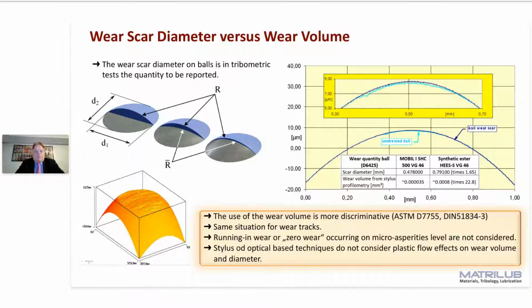And here comes the first problem in tribometry. So imagine these 3 wear scar diameters were generated with 3 different oils. You report the same wear scar diameter. In consequence, you conclude all 3 oils have the same wear protection. But in reality, if you determine the real wear volume by a stylus or by an optical microscope, you see there is a difference in wear volume, which is significant, so all three lubricants don't offer the same wear protection.